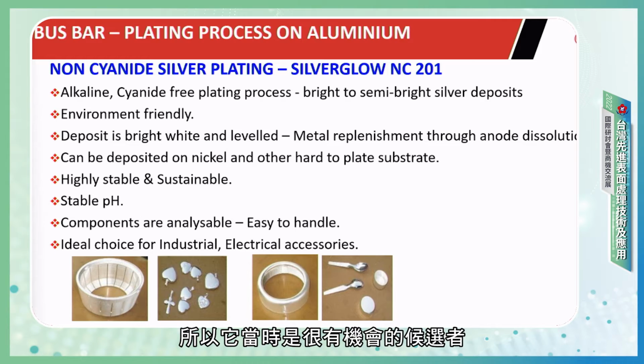So even though at that time it was a very powerful candidate, now in modern non-cyanide silver formulations, supply houses have slowly started to remove or eliminate it as a complexing agent. We are using a different one, free from succinimide. It gives a much more stable complex, and we have also seen that the tarnish resistance is much better than earlier generation non-cyanide silver processes.